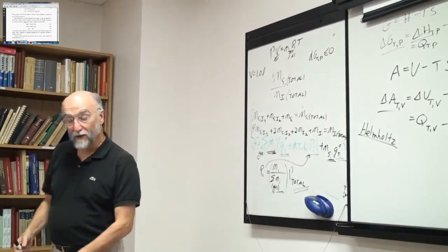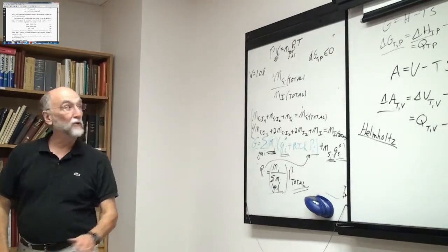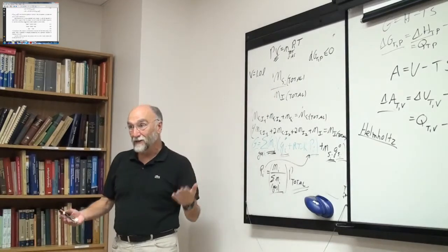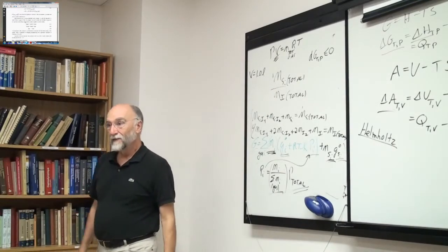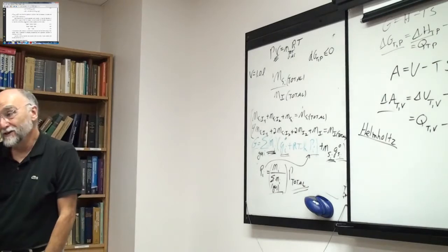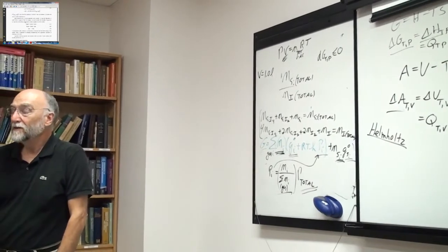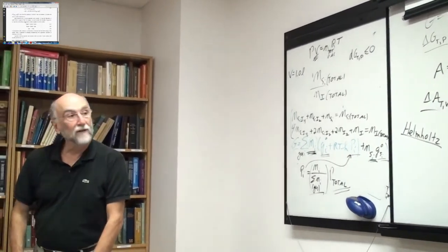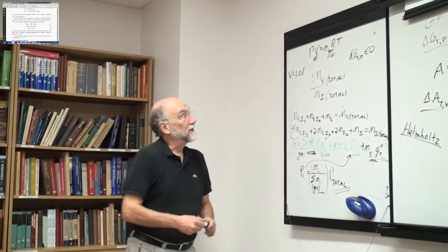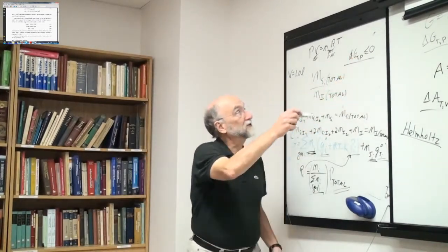You're trying to calculate equilibrium at this higher temperature, so you would guess what the higher temperature was, let the thing reach equilibrium and see if it was actually adiabatic or not. If it wasn't, then you go higher or lower until you ended up with the temperature. Okay. So that's why this is what I said earlier, that this is the most practical